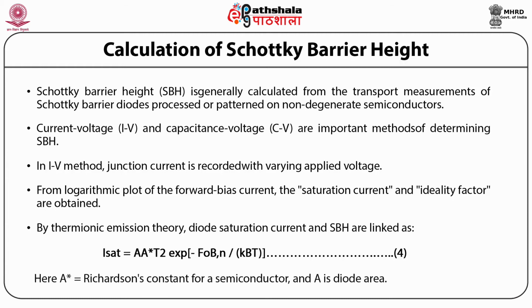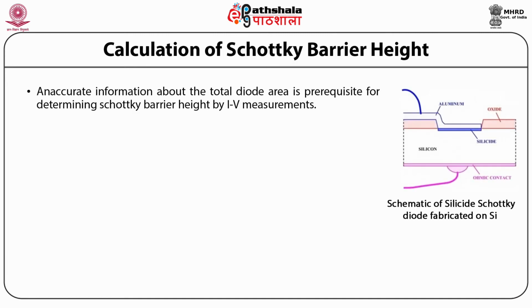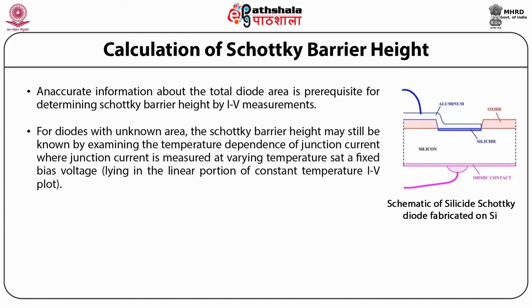Here, A star is the Richardson constant for a semiconductor and A is the diode area. Accurate information about the total diode area is a prerequisite for determining Schottky barrier height by IV measurements. For diodes with an unknown area, the Schottky barrier height may still be known by examining the temperature dependence of junction current, where junction current is measured at varying temperature, at a fixed bias voltage that lies in the linear portion of the constant temperature IV plot.